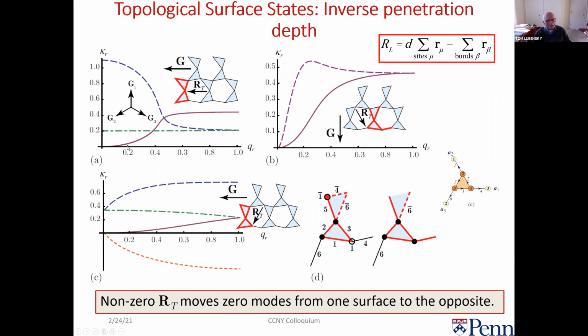There are four. This line here is basically an acoustic one where the inverse penetration depth goes to zero, or the penetration depth goes to infinity, and this is doubly degenerate, and they're the two modes here. This one is the symmetric one. The two ends are the same. I have two zero modes on each surface. And here's one where I have three zero modes on one surface and one zero mode on the opposite surface. So just by fiddling around with this structure, you can get that behavior.